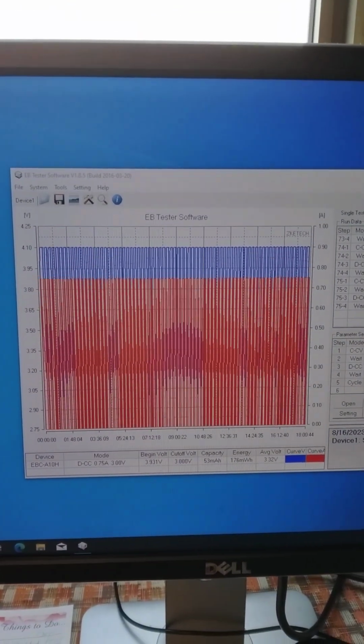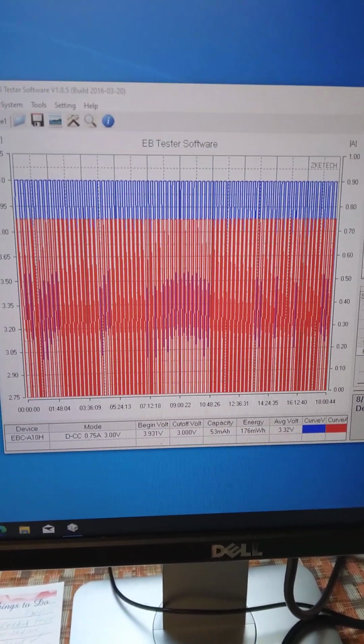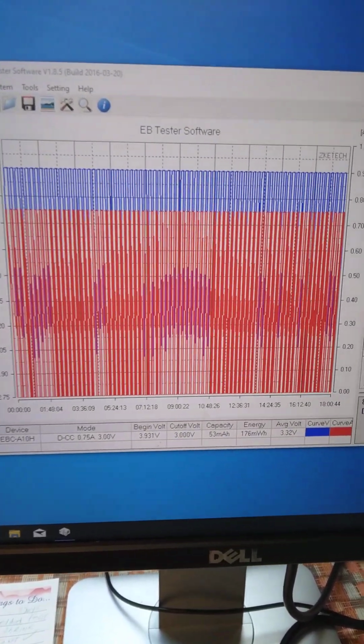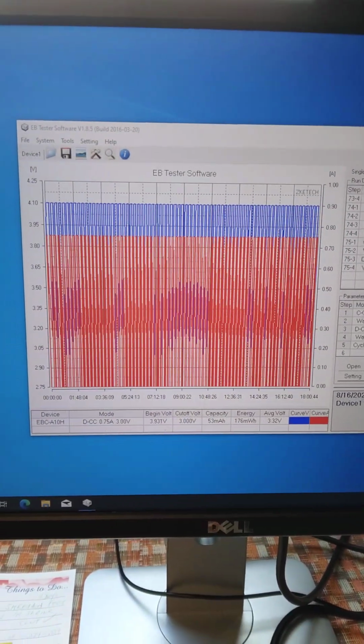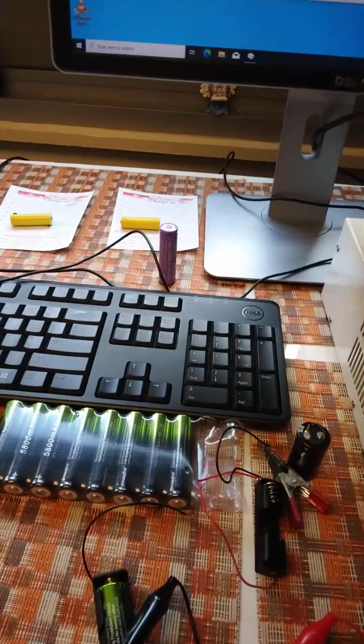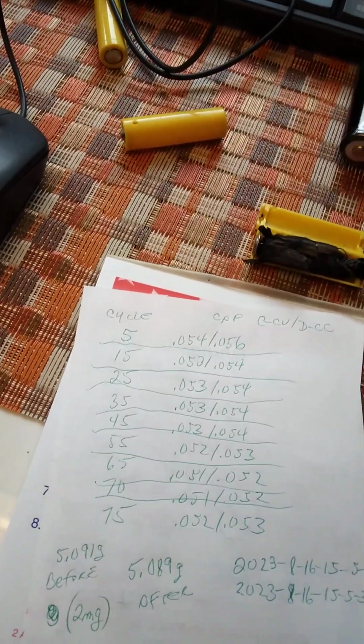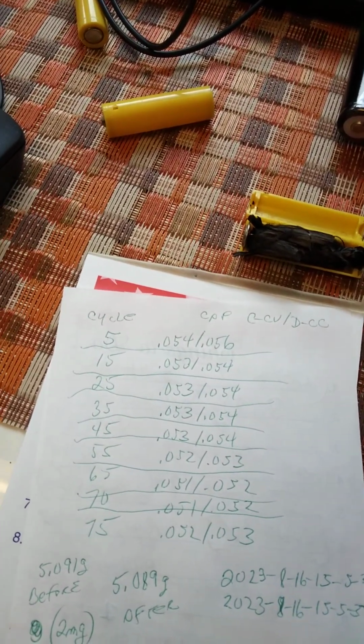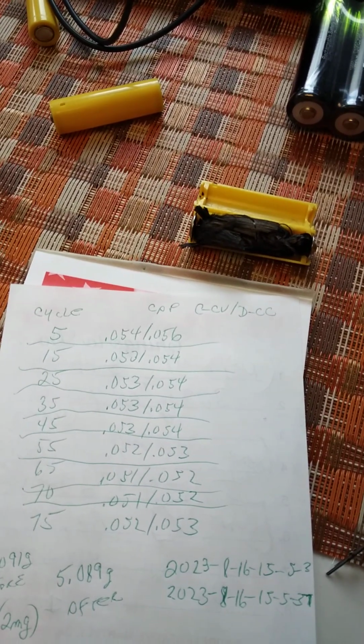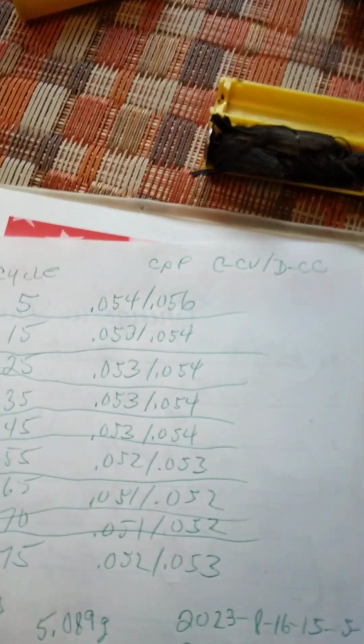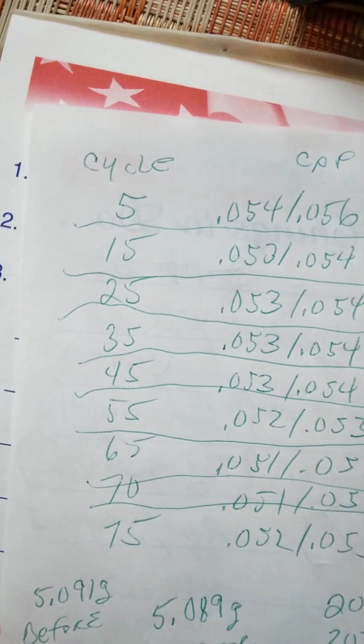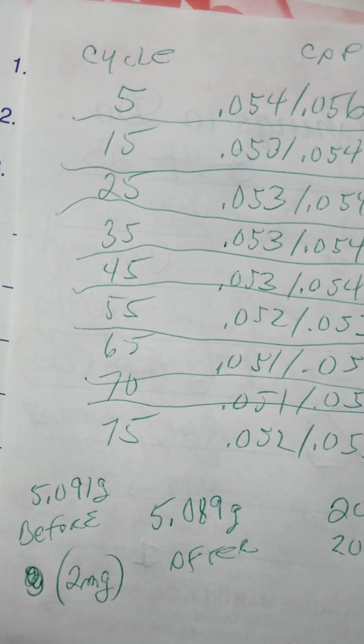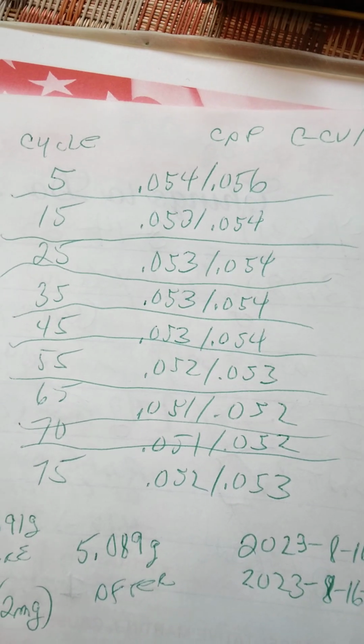So the dry run, you can see completed. To my website, I will put the data and this graph, and it performed pretty well. Here are, and I'll put these in the write-up, capacities for the charge, constant voltage, and discharge, constant current. And if you can see my handwriting there, I've selected cycles 5, 15, 25, all the way up to 70, and then 75, taking data points pretty good.